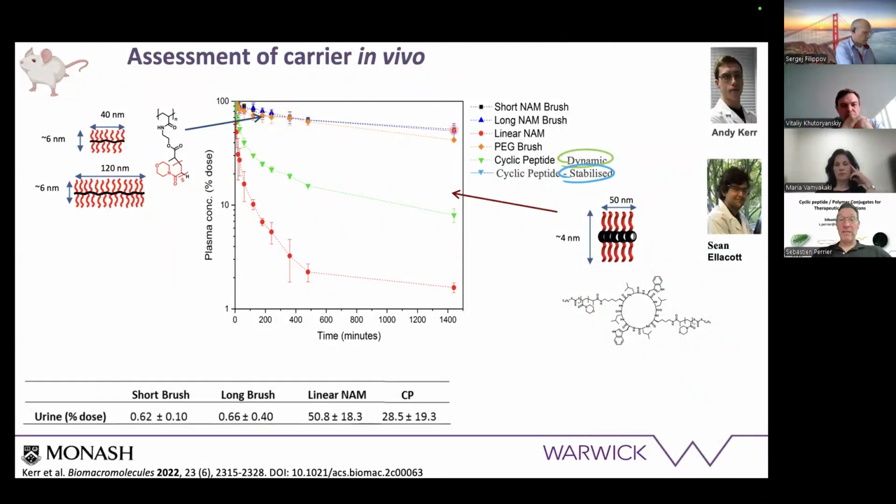And this is an issue. This is an issue for nanoparticles. We have accumulation. Those things tend to not come out. In fact, if you measure the amount of material that you collect, for instance, through urine of the animal, you'll see that independently of the size, so even for small structures as well as for big structures, we're collecting about 0.6 or 0.7% of the material after 24 hours. So this is a problem because we have effectively accumulation, and that could lead to toxicity.